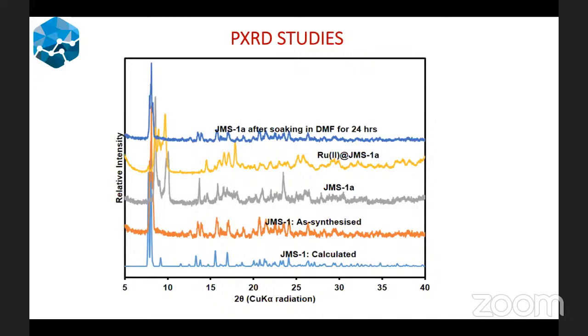But upon functionalization with the ruthenium p-cymene complex, Ru(II)@JMS-1a, you can clearly see the appearance of some new peaks, which shows a structural transformation that took place. And of course, if you take your activated material and soak it in DMF for 24 hours just to check for reversibility, you can clearly see that there is total reversibility in that transformation.